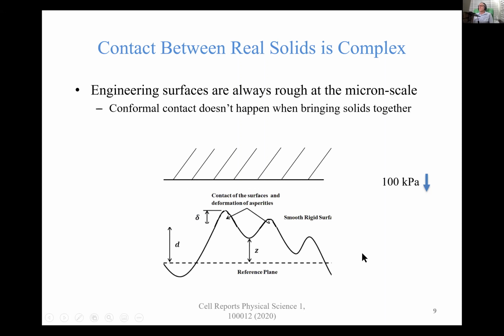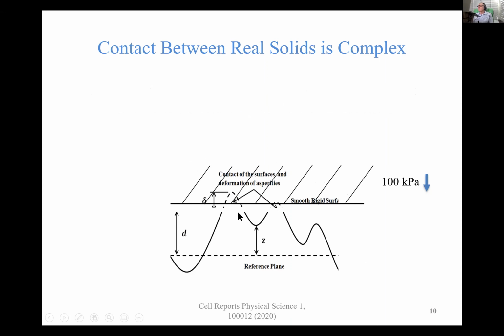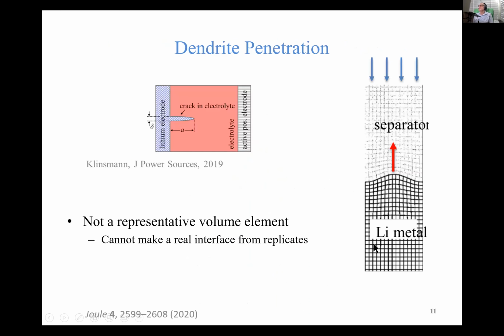But if you think about a real surface, then when you bring real surfaces together, initially they contact just at the peaks of the tallest asperities. The pressure at those contact points can get very high. It can go up to, say, the yield strength of the material. And so let's imagine a case where the yield strength of this material is 100 times greater than the stack pressure. If you have a situation like this, then the entire load is going to be carried by just 1% of the surface. And so you never approach anywhere near conformal contact. And this is the sort of contact situation that you have in many real life situations.